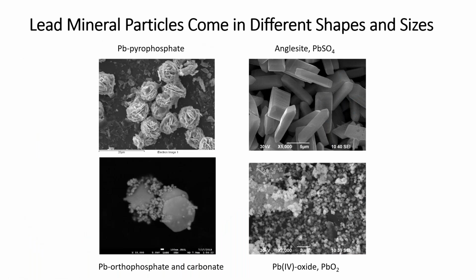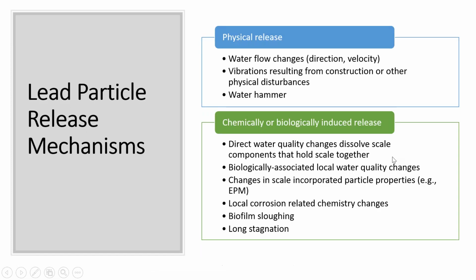Particles come in all kinds of shapes and sizes. I just wanted to show you some pretty cool images we've taken over the years. Lead pyrophosphate solids here look like roses or something like that. Anglesite is often found at lower pH conditions, maybe at the interface of a leaded solder joint. I showed you the lead carbonate and lead phosphate, how different in size they can be. And lead 4 oxides are actually very small as well, so this gives you a sense of different size particles.